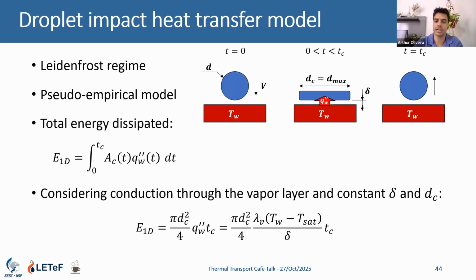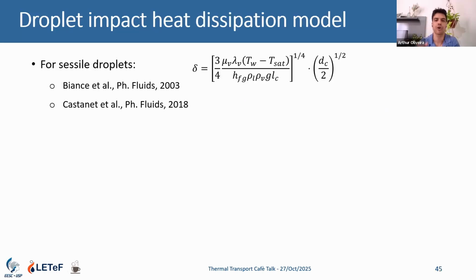If we consider heat conduction, we have heat conduction through the vapor layer, and the vapor layer thickness plays a role here. For the scaling law, let's not take the vapor thickness for an impacting droplet, but for a sessile droplet for a moment. That's a quite well accepted model in the literature, as reported by Anne-Laure Biance and Guillaume Castanet.